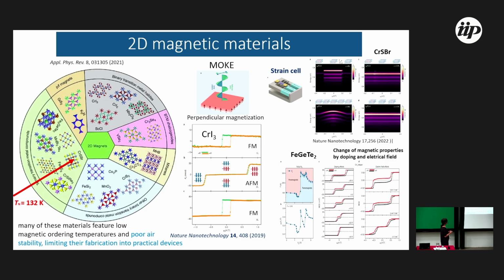But these 2D magnet materials are very interesting. They have different properties. They can have easy magnetization in the plane or perpendicular, or the magnetic properties can depend on the number of layers. For example, for this material, the magnetization is perpendicular. If you have one layer, it's ferromagnetic, two layers, antiferromagnetic, and so on. And you can modify these magnetic properties with, for example, strain. You can use a strain cell and just apply strain. It's antiferromagnetic, but with strain it can become ferromagnetic.